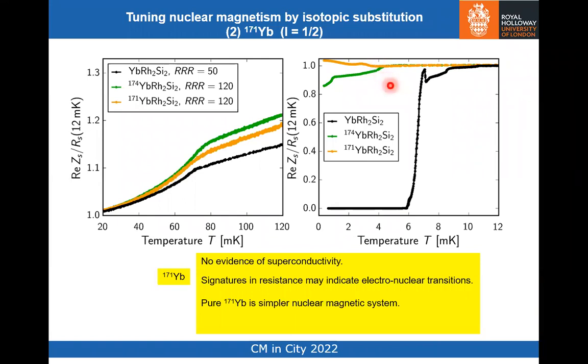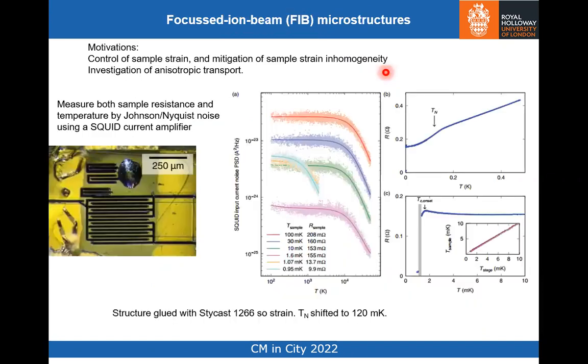So the fact that there should be a magnetic transition is not surprising. There's an indication that we can see that in the resistivity, but there's no superconductivity. Then there's a bunch of other work on focused ion beam microstructures that, given the pressure on time, I will just whiz through. The initial sample was this long meander.